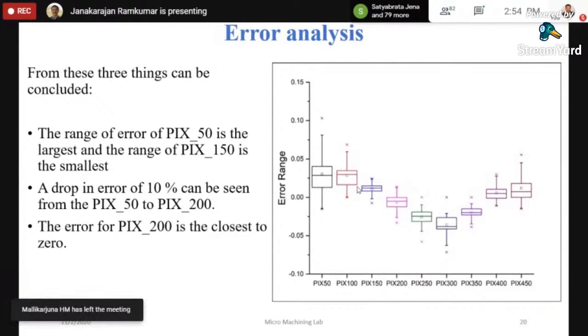So from these three things, what we can conclude is the range of error with pixel 50 is the largest, and the range of 150 is the smallest. So the more pixels, the more data you get. The drop in the error of 10% can be seen when you take pixels from 50 to 200; there is a variation you can see here. So here I am talking about pixel 50, 100 correlation.